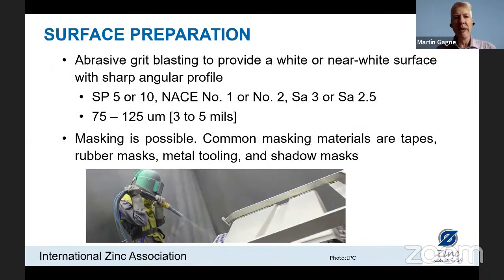So now for surface preparation, again, it's grit blasting, which is key. This is the key requirement for surface preparation. We need to have this sharp angular profile. Now, Graham had talked about the SA3, which is a white metal surface preparation. SA2.5 is a near white metal. And SSPC, the Society for Protective Coatings in North America, they also have a white metal or near white metal designation, SP5 or SP10. The same with NACE. SSPC and NACE have now joined to form AMPP, but NACE number 1 or number 2 surface profile, this is white metal or near white metal. But the angular profile, we want to have 75 to 125 microns, anywhere from 3 to 5 mils.